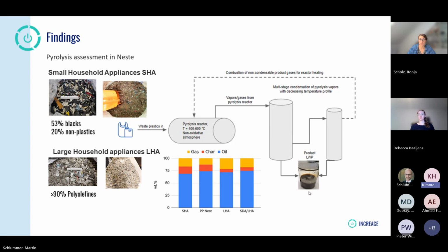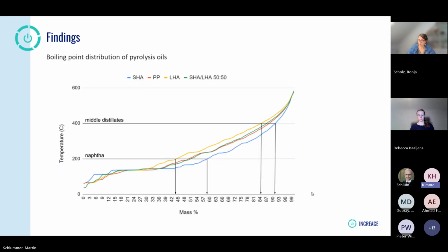And the next slide shows the boiling point distribution, just to give an idea. It's a very wide boiling point distribution, the combined liquid product boiling between 50 and 600 degrees, but about 50% is in the so-called naphtha region below 200 degrees boiling point, and then up to 90% is either naphtha or middle distillates, not heavies. So usually the naphtha is of course the easiest to feed to the steam cracker.